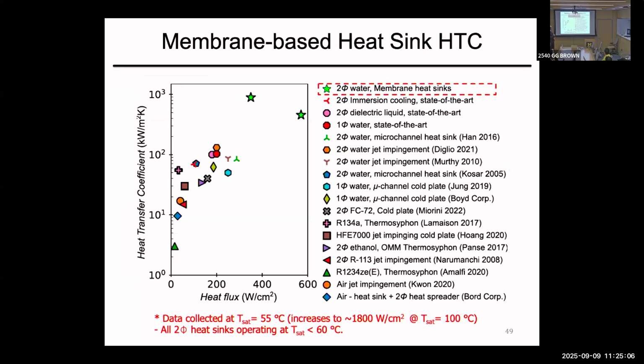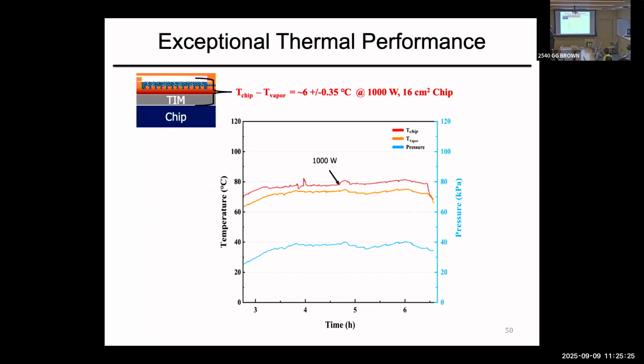So let's look at the water. It's just off the chart, that membrane-based scenario relative to the heat flux. In the long term, you can address the heat flux issues as well as a high heat transfer coefficient. But can you really address the system-level issues we discussed? As an example, we tested a chip with this heat sink, and the total temperature difference between the backside of the chip and the vapor is roughly 6 degrees. Right now it's like 30 degrees. So it's really transformative. You could maintain the backside of a 1,000 watt chip, the latest generation of NVIDIA that will come to market shortly.